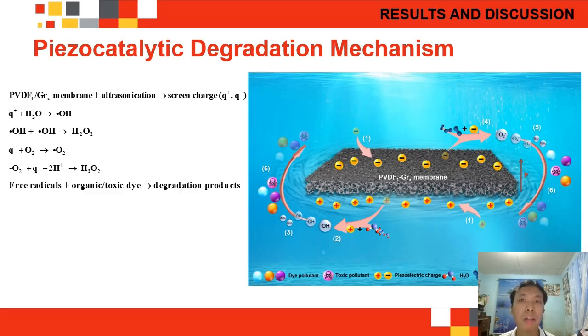Although alpha PVDF crystalline phase still possesses some electroactive phase, the limited screen charges hinder the effective generation of ROS species and reaction with pollutants, resulting in lower degradation performance. Conversely, the addition of graphene powder induces molecular change of PVDF to form the piezoelectric beta phase, establishing the strong piezoelectric field in the process, consequently achieving highly efficient dye degradation. So we can see from equation 1 to 6, the corresponding chemical reaction process.